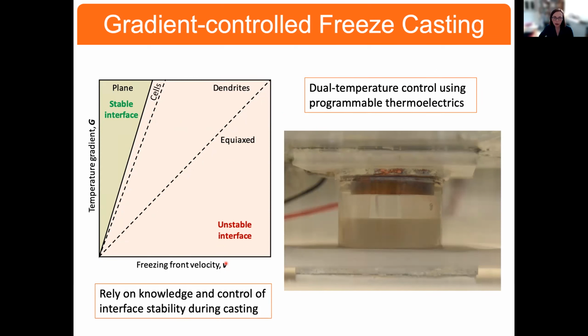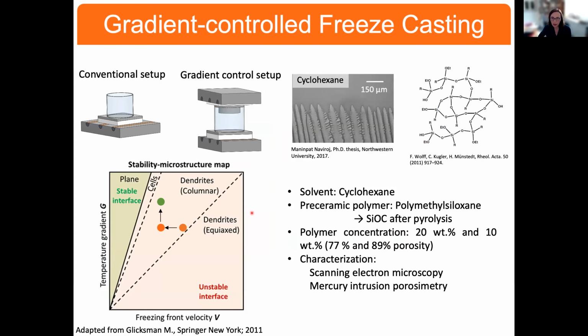So if we need to control both freezing front velocity and temperature gradient, one way to do this is not to just have a cold plate. This is an actual photograph of our freeze casting setup. So here's our cold plate on the bottom. Here's the mold. But we also put a second thermoelectric here on the top. And that allows us to have dual temperature control in which we can program to keep both the temperature gradient and also the freezing front velocity constant. It also gives us an opportunity to move around this region.